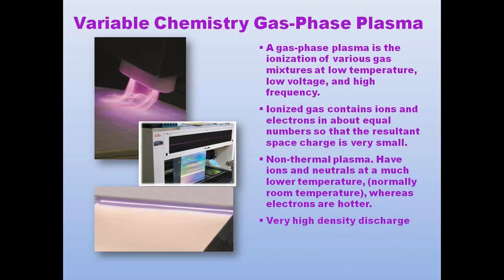And as opposed to vacuum plasmas, variable chemistry gas phase plasmas in atmosphere have a very high density discharge. And so what you can expect is a very low dwell time relative to the exposure to the material surface to get a very high surface energy effect.